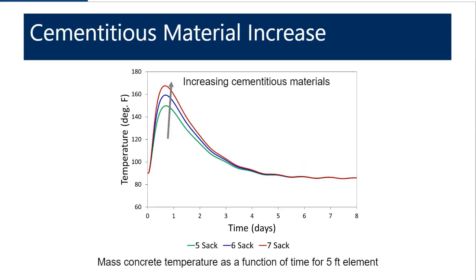The cementitious materials similarly have an effect. And so now this graph is showing the impact of increasing the total amount of cementitious material, or the cement plus SCMs in the mix. And I'm showing here, for example, an increase from a 5-sack mix, which has 470 pounds of cementitious material, all the way to a 7-sack mix, which would have 658 pounds of cementitious material per cubic yard. And what you can see is, just like with increasing the dimension, as you increase the total amount of cementitious material in the mix, there's also an increased potential for temperature rise.